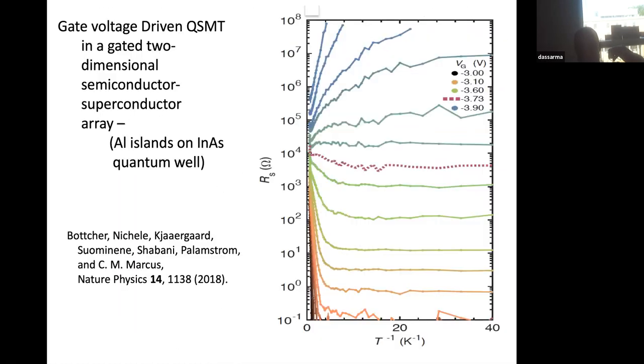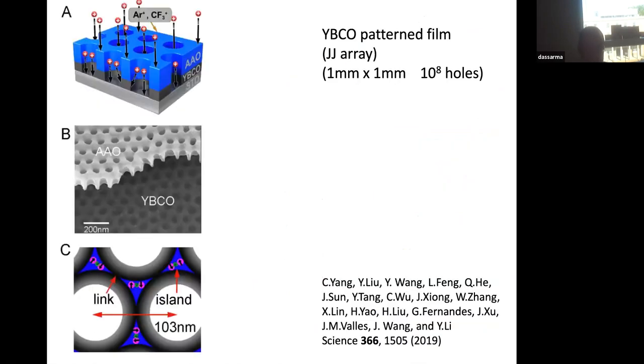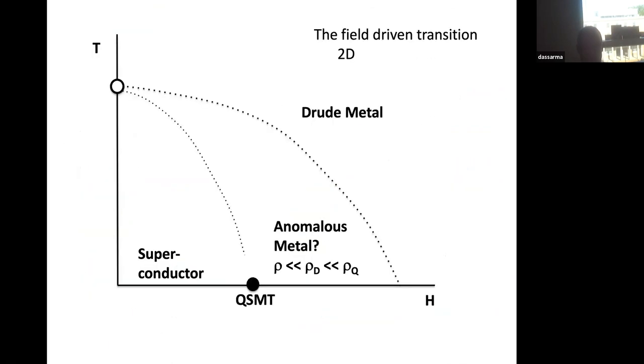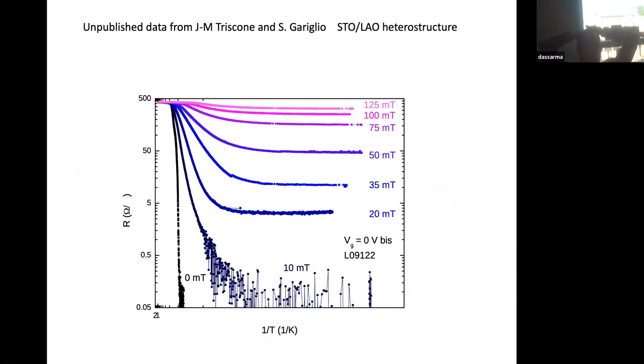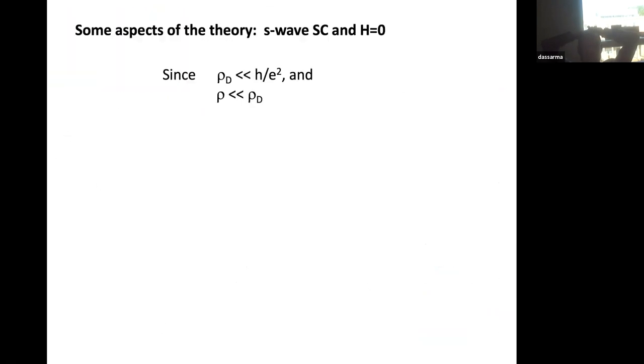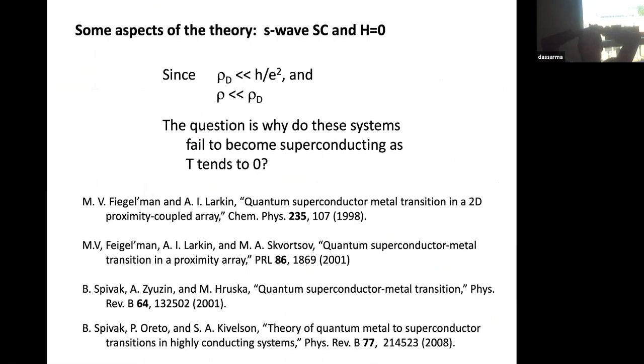Now, going back to the theoretical question, experimentally, I think things are pretty clear, and I think you made a very good case that this metal, if anything, is not like any metal we know in two dimensions. But theoretically, again, one can question, but you can do an RG, particularly if the interaction is weak. And this RG is not trivial. It's not a one-parameter RG, but this was the program started by Finkelstein, who tends to be, you don't get much talking to him, but this is something I have done also. If you do RG on the weak localization scaling picture, throwing in interaction, at least in weak coupling RG, the picture doesn't change. Meaning the details may change, but the fixed point survives. No, there are no fixed points. You flow. You conclude, we are in 2D, that the insulating phase survives. I mean, there is no reason to question it.